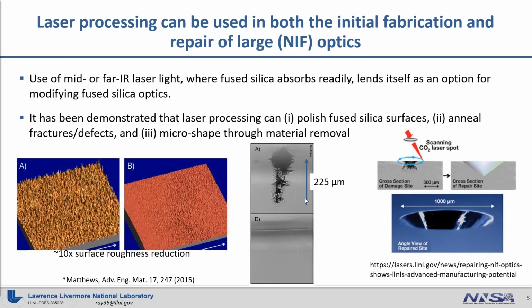If we go to the middle figure, if you look at the top panel, it's not quite so clear to discern what we're looking at, but this is a cross-section of fused silica at an angled view. The white bar or my blue arrow designates the top of the optic, and traveling down along the z-axis, you're going into the optic. Illumination with mid-IR laser, shown in panel D, basically anneals out the defect, or you heal your fused silica. Or on the right-hand side, if you want to do a very thorough repair, if you take a CO2 laser and raster scan it around a laser damaged site, you can utilize material removal to micro machine or micro shape your fused silica. In that image with the 1 millimeter bar across, I just think that's a cool image. That's showing your canonical pit after this micro shaping. And so those are ways that laser processing can be used.